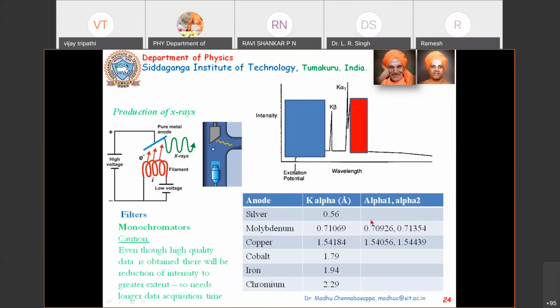And then what is the use of using different metals? If I use different metals, then I can vary the wavelength of the X-ray which is generated. For example, if I use silver, then the wavelength of X-ray would be 0.56 angstrom. Okay, so this is for only pure K alpha radiation. And if I use molybdenum, this would be something like 0.71, and then copper would be giving 1.54, cobalt would give 1.79, iron would give 1.94, and chromium would give 2.29 angstrom wavelength of X-rays.